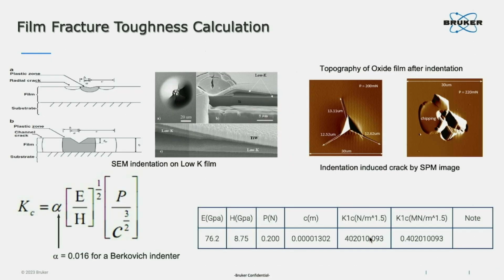We can measure the crack length by post SPM image. We can calculate the KC, the fracture toughness, by our machine. You see the formula is quite simple. Elastic modulus and hardness can be measured by nano indenter.